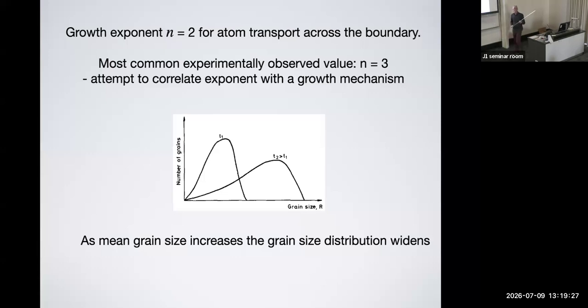And as is often the case with these kind of simple models, people then proceeded experimentally to try to find systems where they have a grain growth exponent that is actually 2. And it turns out that's quite difficult. Most of the experimentally observed grain growth exponents are clustered around 3, but there is a whole range of grain growth exponents. Right? Grain growth exponents do vary from 2 to 4 or 5, and I'll show later much higher than that. So the interesting part is, right, this 2 was derived for the simple atom transport across the grain boundary, but growth, especially if you then have a polyphase material, it can't just be atom transport across the grain boundary because you have different crystals with different composition. So there has to be diffusion going on, which is part of the background.